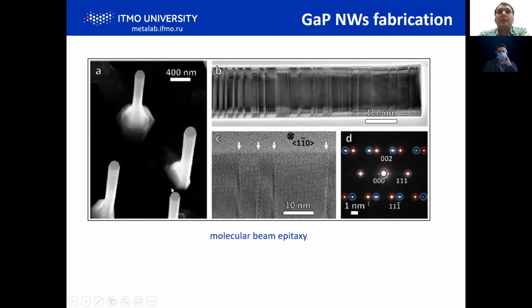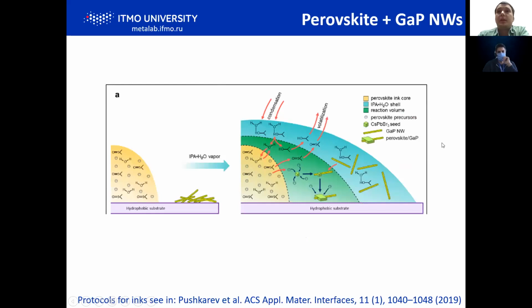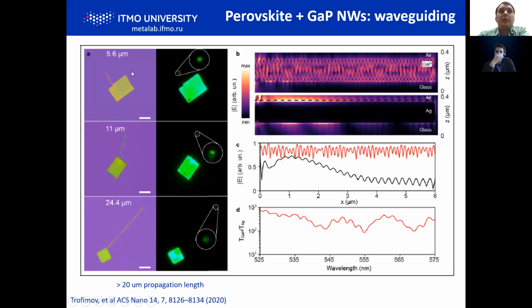Gallium phosphide nanowires and nanowaveguides can be fabricated by molecular beam epitaxy technology, which we also use here at ITMO. And the quality of such nanowires is quite good, and they can be used for waveguiding. Further, we created a solution with these nanowires, and then just put them into a solution of perovskite precursors, and each nanowire works as a seed for crystallization of perovskite microlasers. And finally, we have a high-quality microlaser with an integrated nanowaveguide with a length of more than 20 microns.